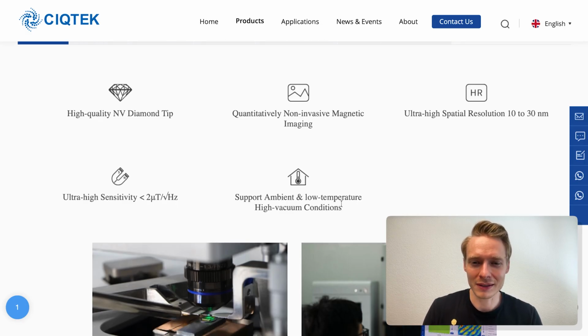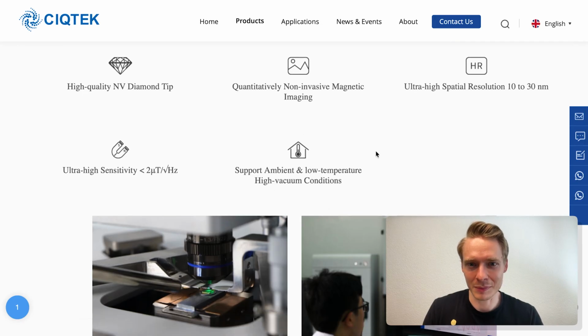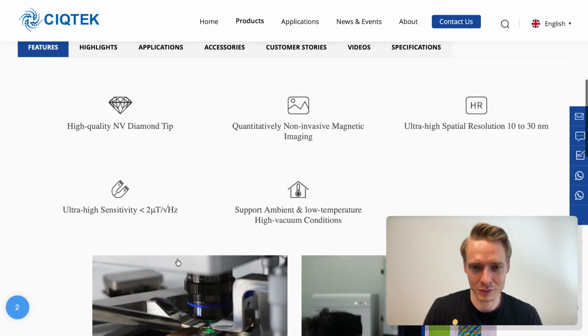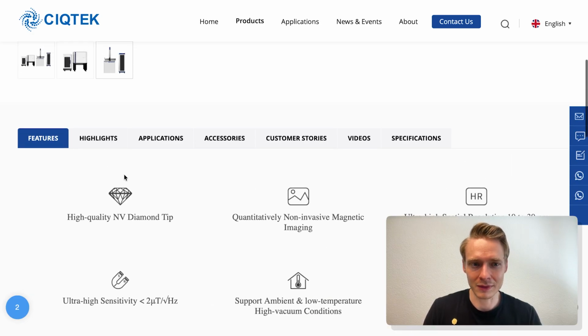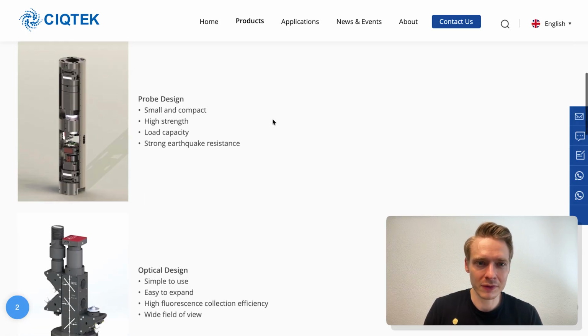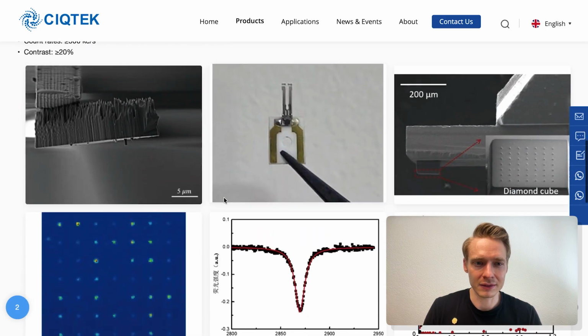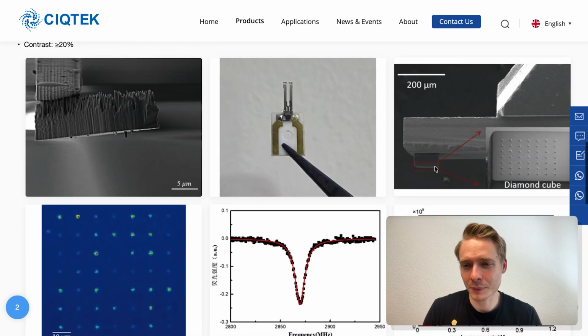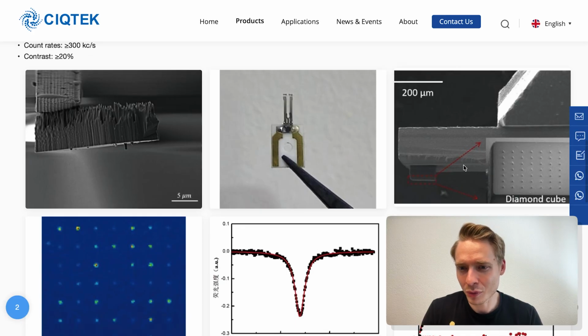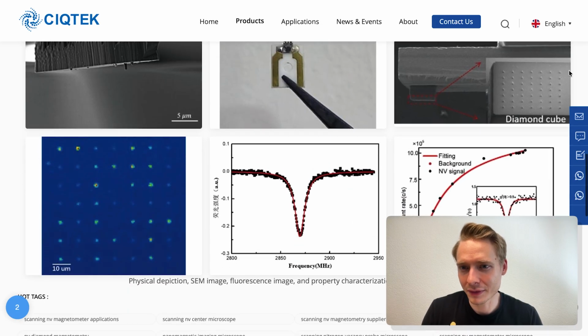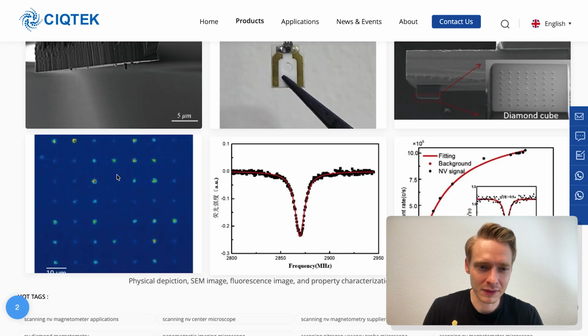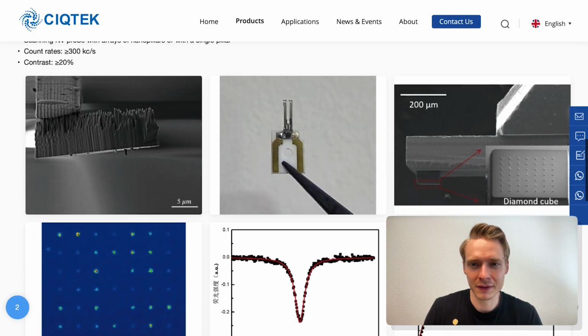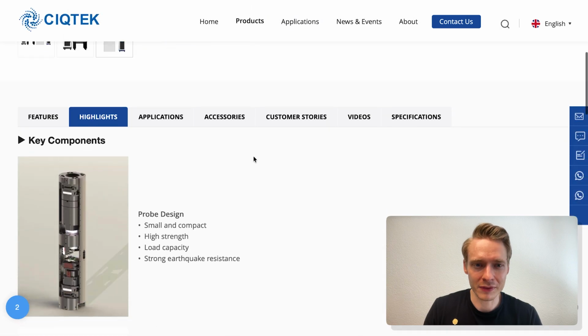And then supported ambient and low temperature, high vacuum conditions. That's also something that I mentioned before, right? So there's a broad temperature range at which this is working, and also high vacuum is a topic here. Here you see the different components, right? So there's the probe design, the optical design. Then I guess you can also see a couple of those images. This one here is very interesting. I think here you see probably this is the cantilever. And then here you see the diamond cube, which might be the tip. And inside the cube, you see those different NV centers down here, which are probably then being used for the measurement. You can also see this image here, where you see them fluorescing, the different dots, the different NV centers. So yeah, that's probably about the tip or the probe of this system.